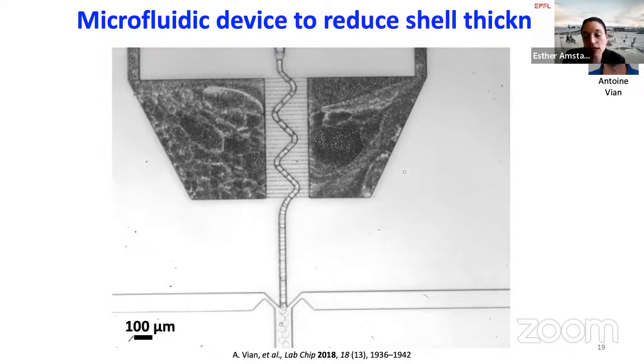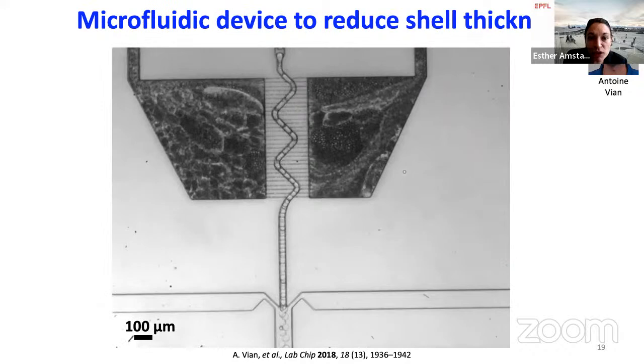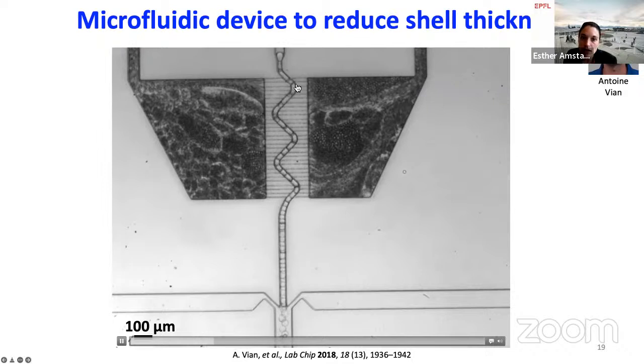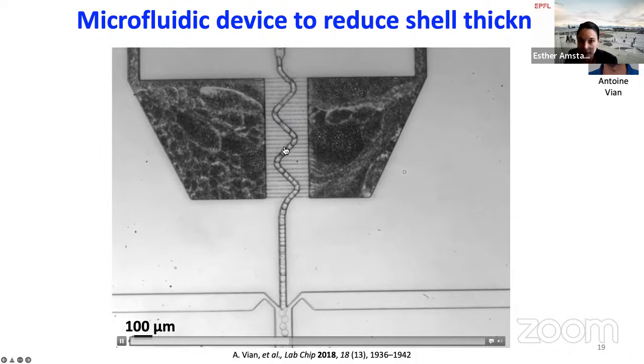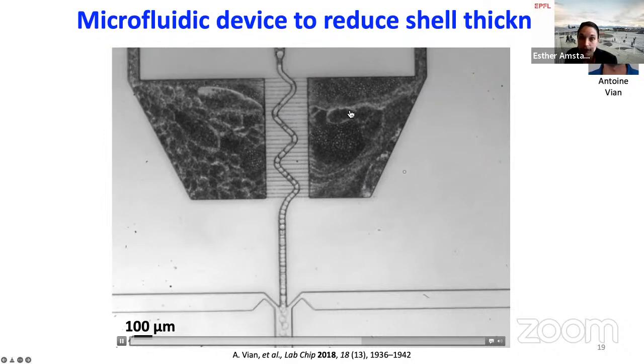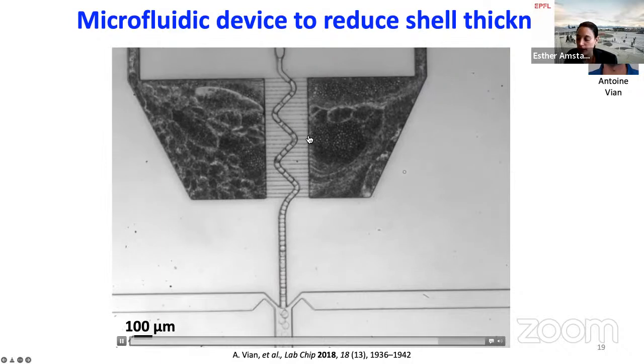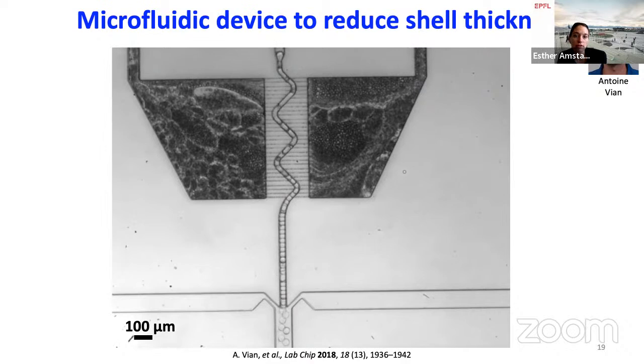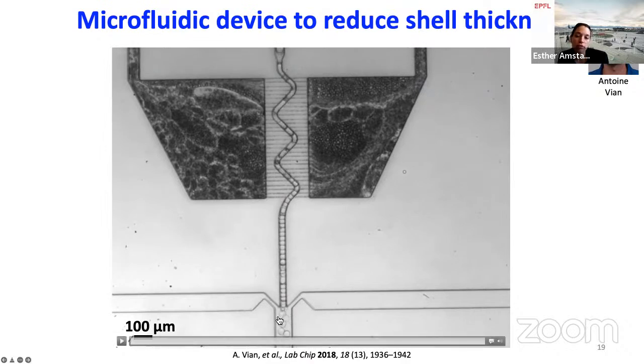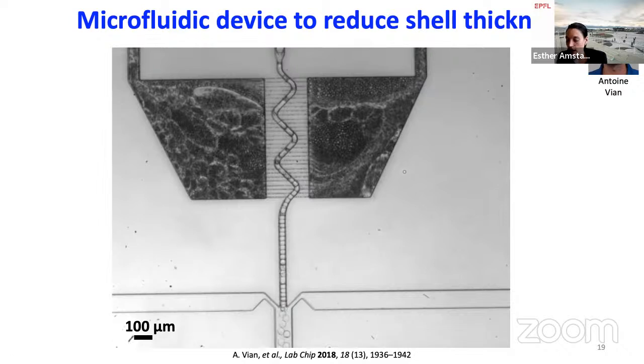And to reduce the thickness of these double emulsion drops, we designed what we called an aspiration device, where we inject these double emulsions into a device where the main channel is intersected by many small shunt channels that are fluorophilic. And these shunt channels are connected to reservoirs that are under pressure. So what we basically do is, like in a Hoover, we suck out the oil from the double emulsions. And there we can suck out up to 95% of the volume of this oil, getting double emulsions that have shell thicknesses of around 300 nanometers at a throughput of, again, about 1,000 drops per second.